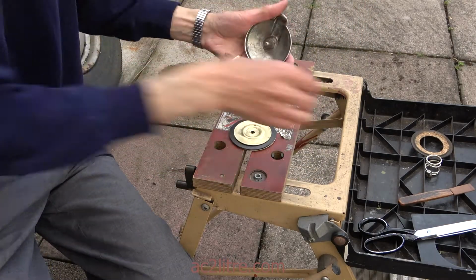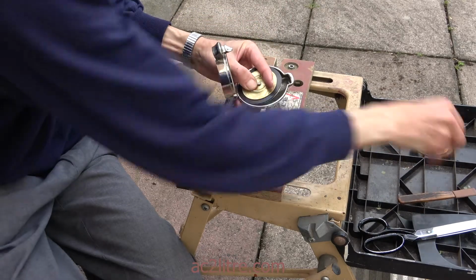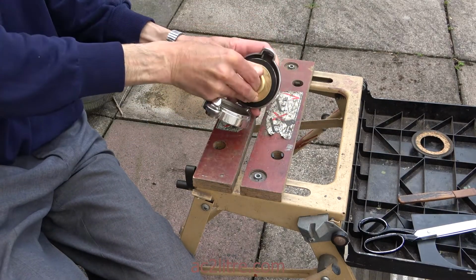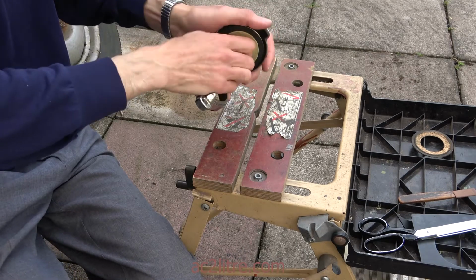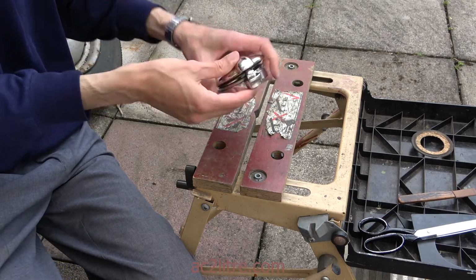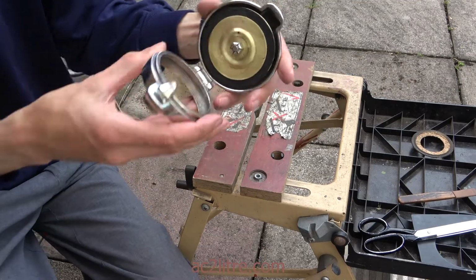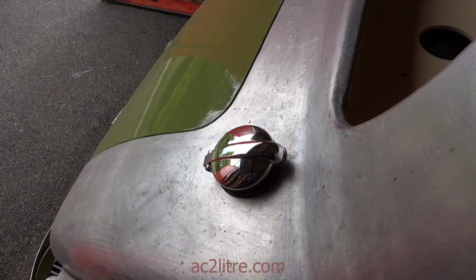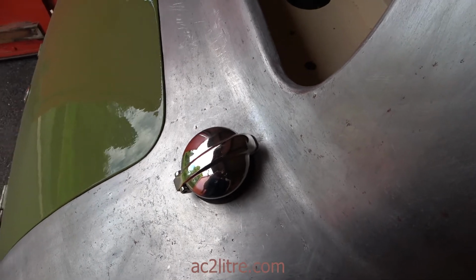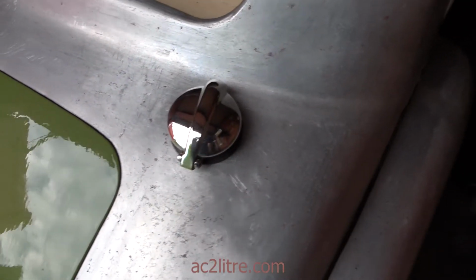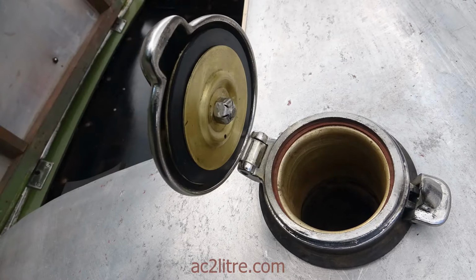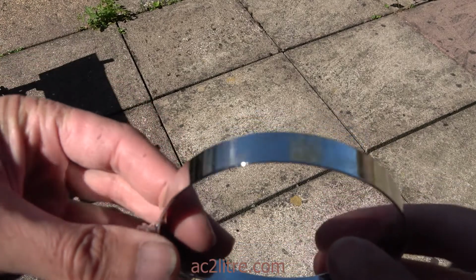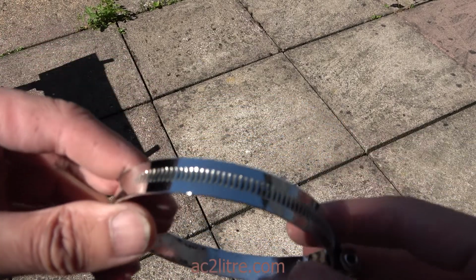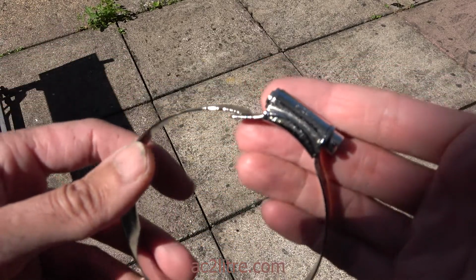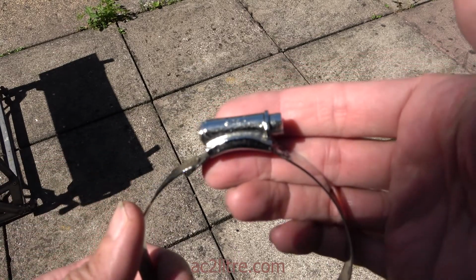As a newbie to this process I did have some slight issues. Some rough plating seemed to be due to not getting the current setting quite right. It is worth measuring the area carefully. Some steel parts were too pitted to be able to give a smooth finish, or rather some of them did not need to look good as they are largely hidden from view. The pitted surface is difficult to get clean enough, with the result that the plating might be left with lots of pinholes, which will quickly rust after the plating. I tried electrolytic cleaning during the prep work, and then soon after plating I smeared wax oil on.